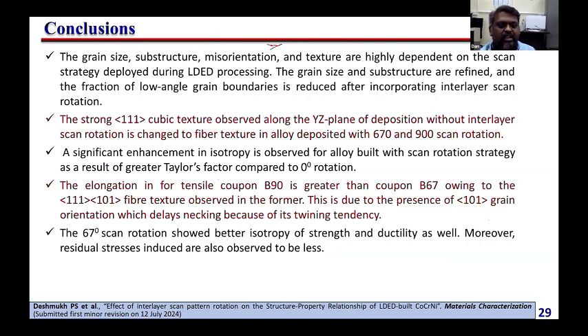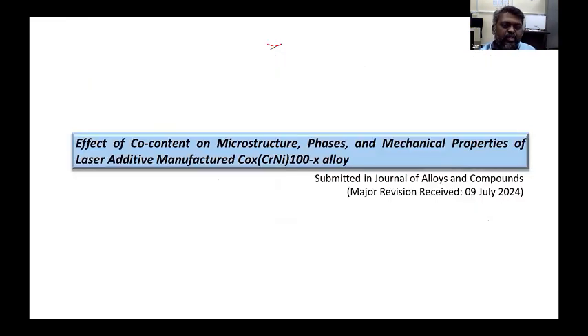This globular grain structure is totally reduced in the 67 degree scan rotation, and we were also able to change the texture. Like in the 67 sample, we observe the 111 and 101 fiber textures, and other fiber textures are there, but there is no strong cubic texture present in the 67 sample. So basically this 67 degree scan rotation is giving better strength and ductility as compared to the other cases. Okay, that's what we understood.